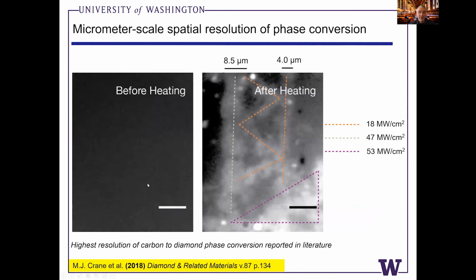So this is a quick illustration of what things look like before and after laser heating. This is the amorphous carbon aerogel in the DAC at high pressure. And it basically has no unique features. It just looks like a black lump of coal. But after we laser heat it, you can start to see a very quick and rapid change in color. At least it becomes much more translucent and scatters a lot more light. And so this is the first bit of evidence that we have that we're seeing a phase change for this material.